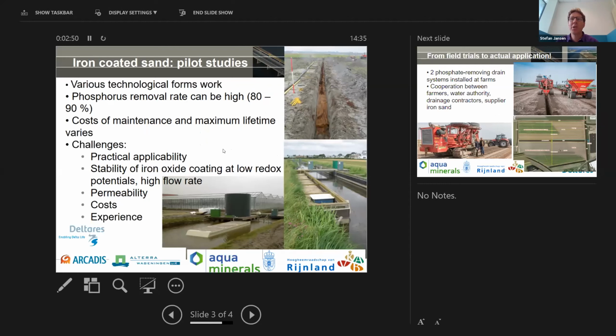Well, this is a couple of pictures of the field pilots that we did with this material. And as you can see, we tested various technological forms for the filter material to be applied. So in the right top, you can see a drain, tile drainage, which is enveloped with iron-coated sand. It has the advantage that you very directly trap the phosphorus before it's coming into the phosphorus cycle, and you don't need any added area of the land, which is very valuable land.